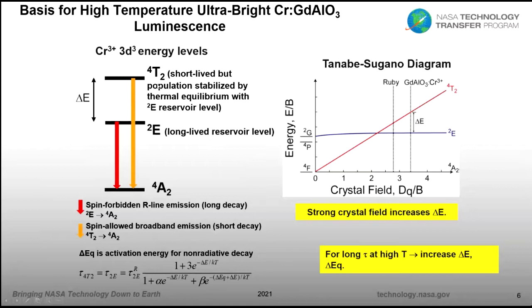Now, just for one slide, I want to show you the physics basis for maintaining this ultra bright luminescence to high temperatures in chromium-doped gadolinium aluminate. When we have the chromium in that lattice, we look at two emission bands. I show the three energy levels. Don't worry about what they're named; I could have easily called them level 0, 1, and 2. With your light, either laser or LED, you can excite electrons into this 2E level, and plenty of people do that. This gives you the well-known R-line emission, fairly sharp, and people have used that for temperature indication.